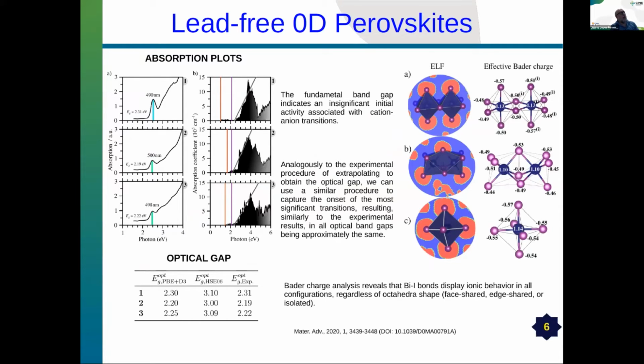What we can see here is that the experimental optical band gap goes from compound 1 to compound 3, with the different cations, from 2.31 to 2.22. Our results comparing the relative difference between the systems are pretty good compared with the experimental results. Then we can understand what's important here, concerning where the states that really make the contribution start.